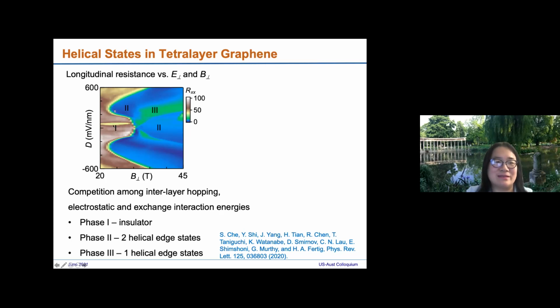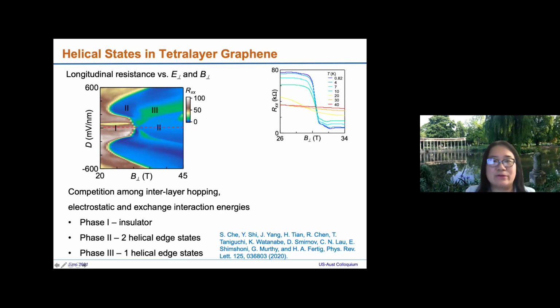Phase one is an insulator. In this case, it's 100, sorry, kilo ohms. So it's 100 kilo ohms, and then it drops to about a few kilo ohms in phase two. And phase three is about 12, 13 kilo ohms. Here we can see there's a pretty sharp insulator to metal transition at 30 Tesla. This shows it as a function of temperature, confirming the insulator to metal transition by the temperature dependence below and also above the 30 Tesla.